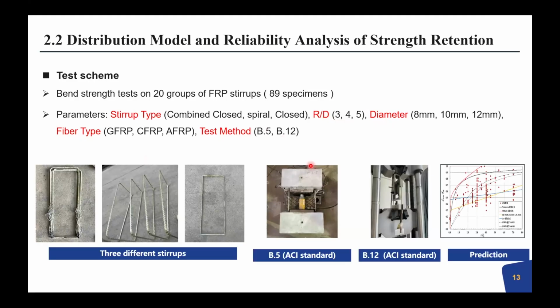Until now, for the standard test method for stirrups, we have two types. They both come from the ACI standard, B.5 and B.12. So we also did different types of test methods. And when we want to determine a more precise function or formula to predict the bend strength, we find, as you see in that figure, a large standard deviation from the prediction. No matter how many parameters we involve, the deviation is large. And also the factors are still very complex for FRP, and there is no standard manufacture method or regulation for this kind of product, causing this issue.